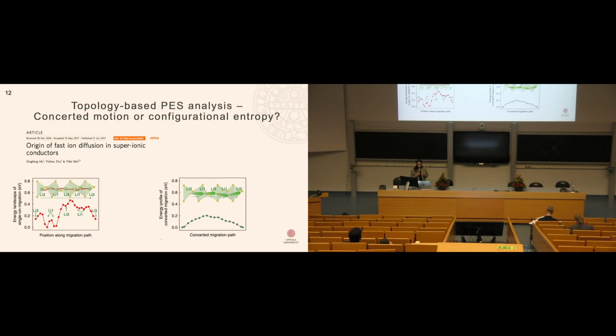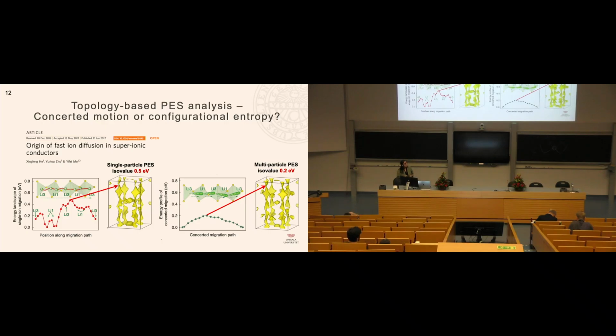Since then, this hypothesis of concerted motion has really been established, that this type of concerted motion is necessary to reach a superionic conductor. But the interesting thing is that we actually see the exact same thing from our single particle potential energy landscapes, where the highest energy barrier is 0.5 eV, when we go to our multi-particle potential, where the highest energy barrier is 0.2 eV, which is exactly what they predicted. But our model is a mean field model, so we would not be able to model explicitly the concerted motion process, which has been claimed to be necessary.